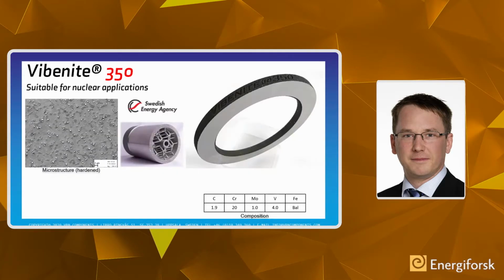We look into Vibenite 350, which is what we think is a suitable material for nuclear application. It is a steel alloy with high chromium content. So you get both wear resistance and corrosion resistance. And today we have a hardness of 60 Rockwell on this material. So it's a good combination material. That is the major thing with this material. We always have fine microstructures, fine carbides, and we also have very, very high cleanliness, and that is the low oxygen content. And that is a patented technology of VBM to reduce the oxygen content, which you always get high when you have powder materials. You need to reduce the oxygen to get good fatigue properties, for example.